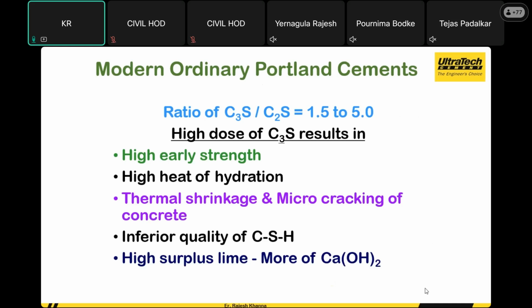So to have high early strength leads to high heat of hydration. High temperature in the concrete will lead to thermal shrinkage and micro cracking in the concrete. That's how when we go for high thick rafts and mass concreting, we tend to bring down the concrete temperatures in a big way, by 10 to 15 degrees, by adding chilled water, or reducing the cement content by 50% or replacing that 50% with mineral admixtures like GGBS, fly ash, and other additives to gain the strength.